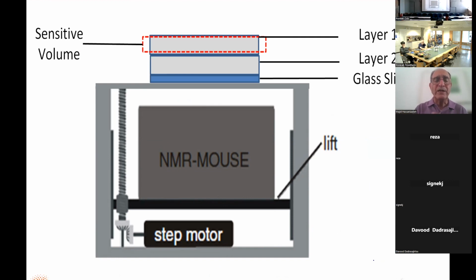This was done at the Procter & Gamble research site near Frankfurt, where we put two layers. You see those are the two gray layers on top of each other, but the upper layer is completely wet. And then we put them on top of this instrument called NMR mouse, a nuclear magnetic resonance measurement, that can measure the average saturation of each layer. It measures it really over the whole layer. So we don't get distribution as a function of X, Y, or Z. For each layer, we just get one average saturation.